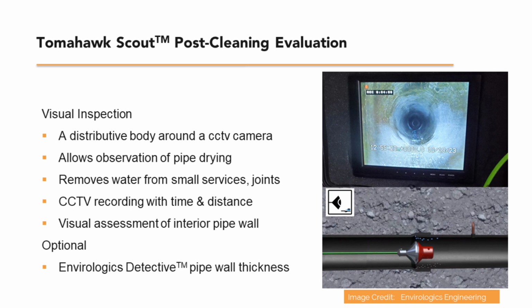We found 2 to 3 hours was generally sufficient to set up and complete Tomahawk cleaning on 6-inch diameter water mains about 130 meters in length. Material collected in the vacuum truck is a mix of tuberculation materials and stone and is more easily disposed of than liquid waste associated with water jetting.